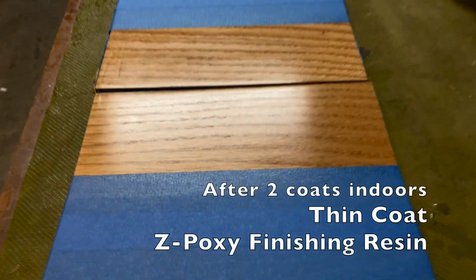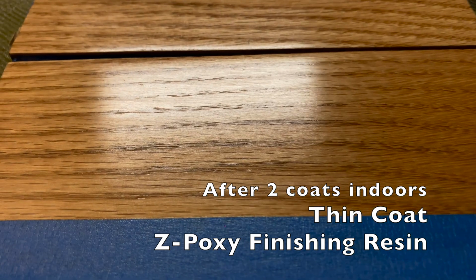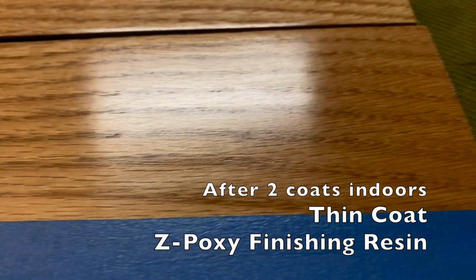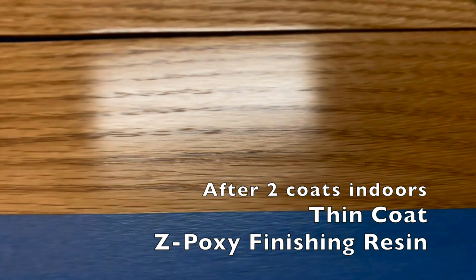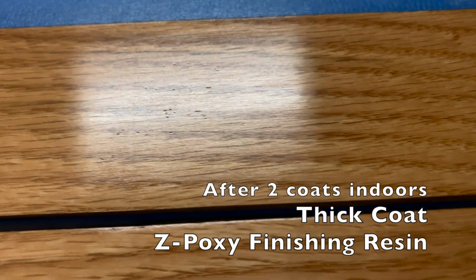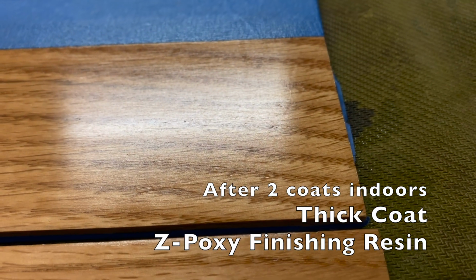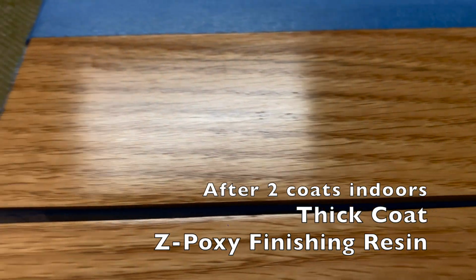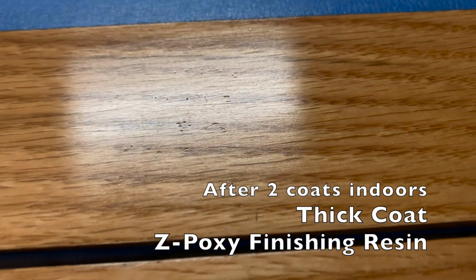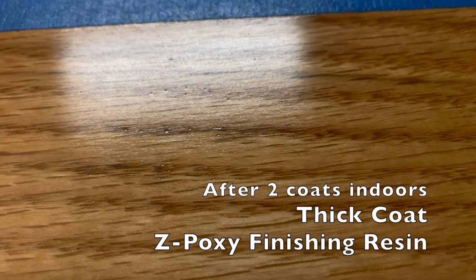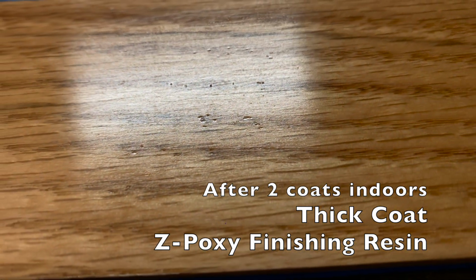Here are the thick and thin coatings of the Z-poxy finishing resin side by side. The shellacked portion of the thin coat board actually looks pretty good. And the heavily coated board also looks pretty good. Some air bubbles did make their mark, however, on the side that did not receive the shellac.